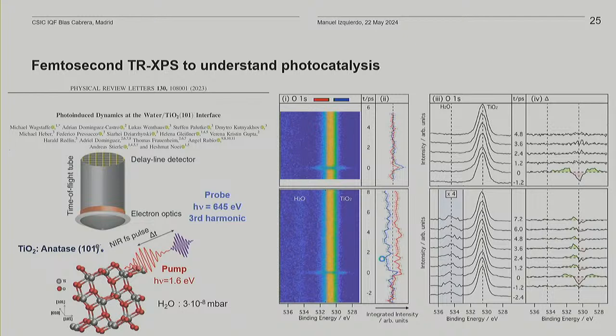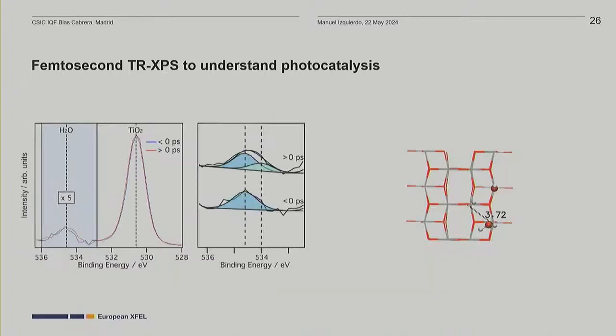Because they had a coverage below one monolayer, you can see here that the water feature is very weak. They also saw that by integrating regions of around 1.2 picoseconds, very quickly after the excitation, the system became kind of stable. So what they did was they add up the spectrum before time zero and after time zero.